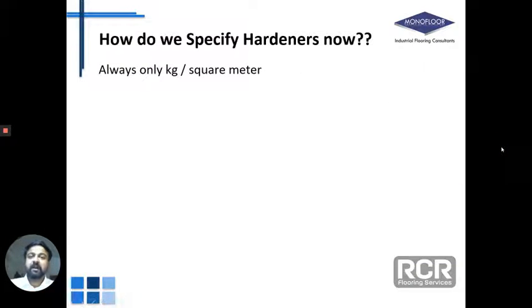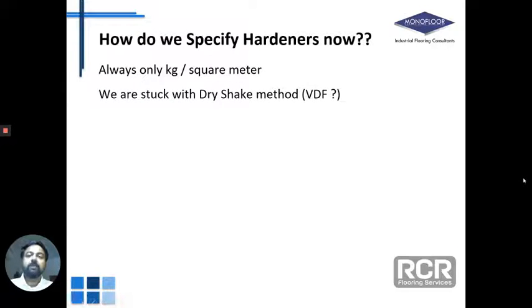How do we specify hardener now? Most of our hardener specification today is to do with kilograms per square meter. So when we have a hardener, we usually specify brands or product names, and we specify kilograms per square meter. But the problem is we are mostly stuck with a dry shake method, particularly when we have a vacuum dewatering. When we try to suck out the water using a vacuum dewatering process, the fundamental that we need to understand is